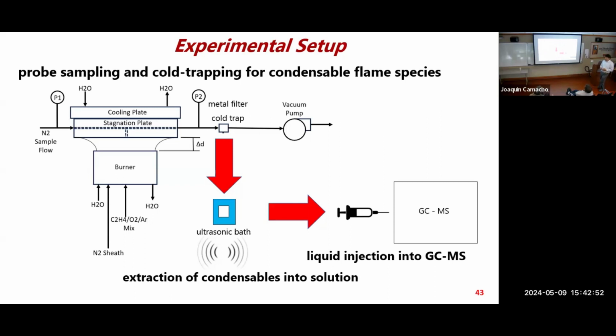In my case, I have a relatively insensitive detector. If I had a more sensitive detector, it would be easier. But this is not as sensitive, so over time we condense this onto a metal filter cold trap. We simply pass this flame sample over this trap at a cold temperature over time. And then we can dismount that metal filter and put it into an ultrasonic bath to shake it up and extract the species from the surface of the metal into solution.